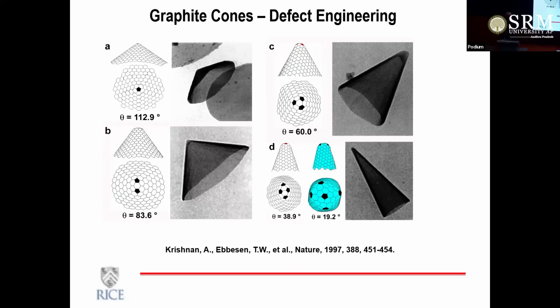So there's also been a lot of experiments in literature reported years ago suggesting that you can actually put 1, 2, 3, 4, 5, these 5-membered defects in the 6-membered hexagonal lattice of graphene, and you can create all these beautiful morphologies of graphite. In fact, this particular paper that was published in 1997 shows that you can really mass produce these type of conical shapes or flat graphitic sheets from the oil and gas industry, the waste of the oil and gas industry. Again, there was no real application found at that point of time.